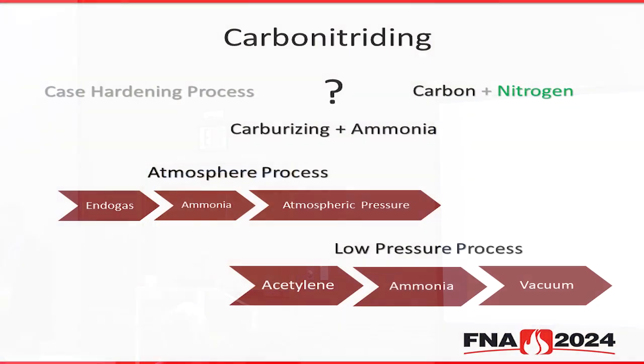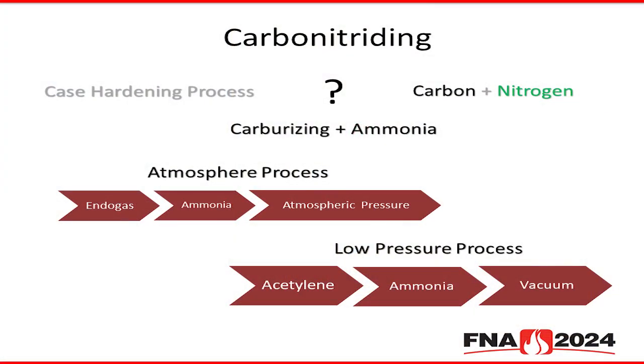So, carbonitriding. Some of you may have attended the first session where Jack Kaluki discussed ferritic nitrocarburizing, which is a nitriding-based process. Carbonitriding is a carburizing-based process meant for case hardening. But in this case, we're tweaking it a bit because we add nitrogen. How? We add ammonia right to the process. So in the process of doing that, we're allowing the ammonia to dissociate.